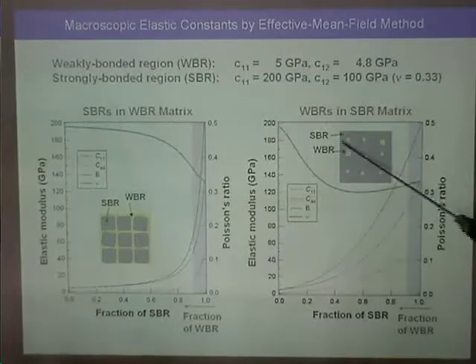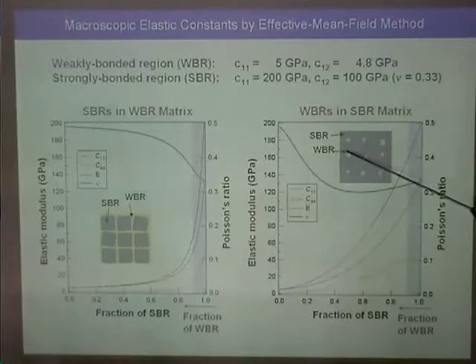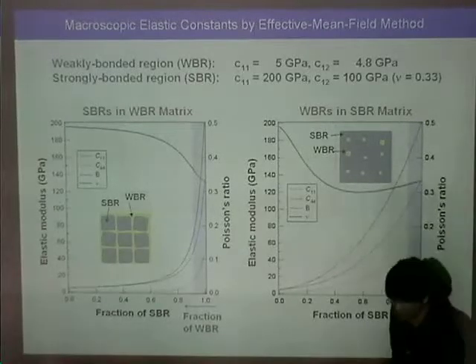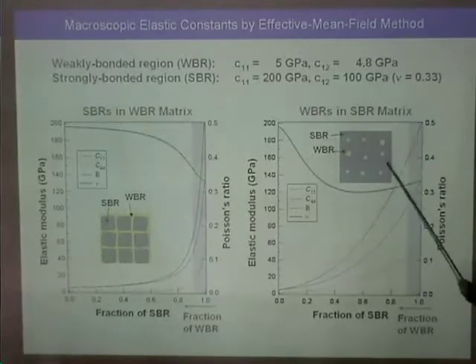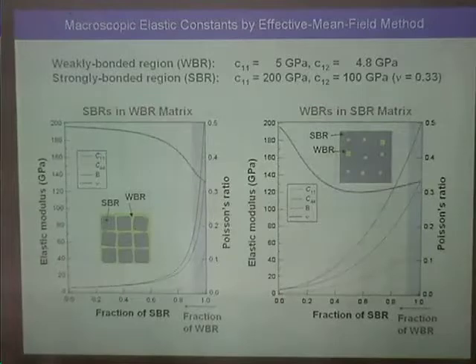So, on the other side, the WBR is included in the SBR matrix, so the elastic constant decreases almost linearly. Therefore, I think that this model cannot explain this drastic change of the elastic constant. Well, that can only not explain the data if you presuppose that because the density change in the strongly bonded regions is small, the elastic properties there cannot change significantly, which is sort of what Dan was asking. That's right. I think it's only given the assumption that all the modulus change has to come from these weak regions that you can argue it has to be the thing on the left, but that's not so obvious.